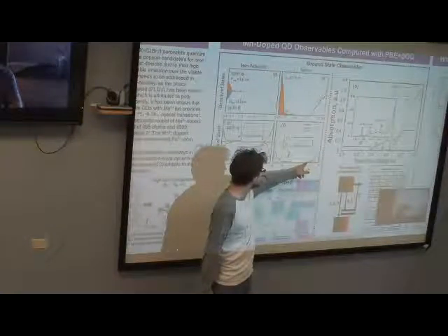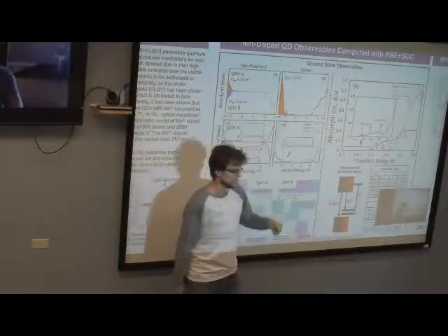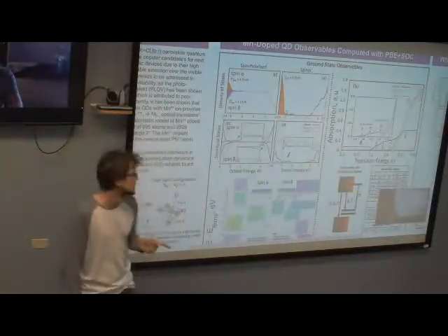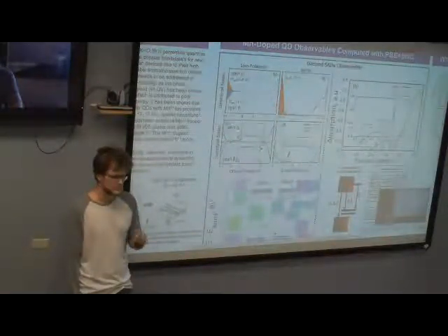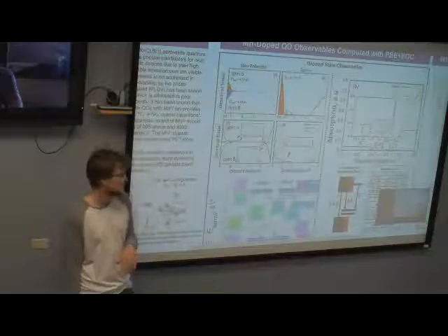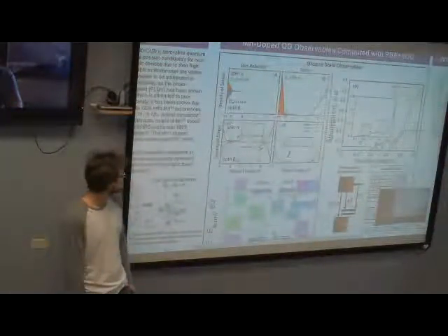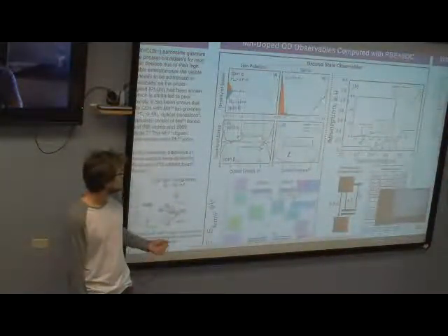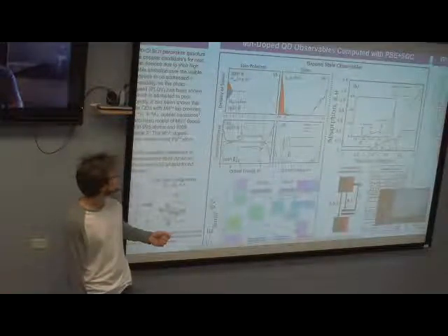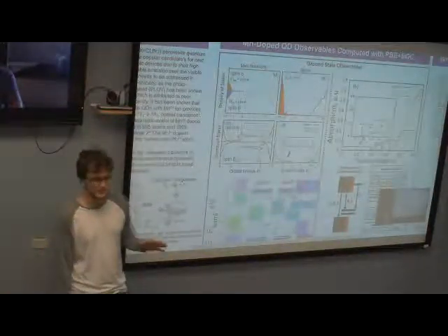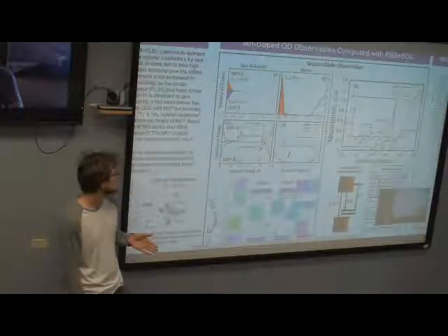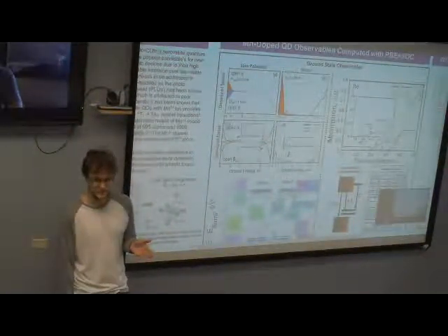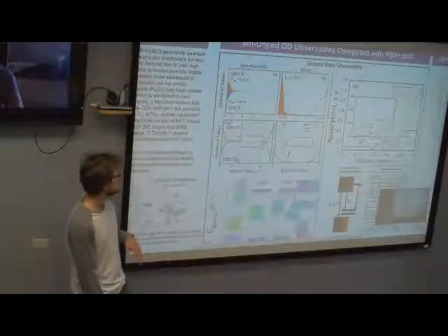So basically we have the wrong energetic alignment for spin flip transitions, if it is the case that it is D to D transitions that are observed experimentally. So using a GGA functional with spin orbit coupling, we can qualitatively get the right valence band electronic structure, but for the conduction band, it doesn't work as well.